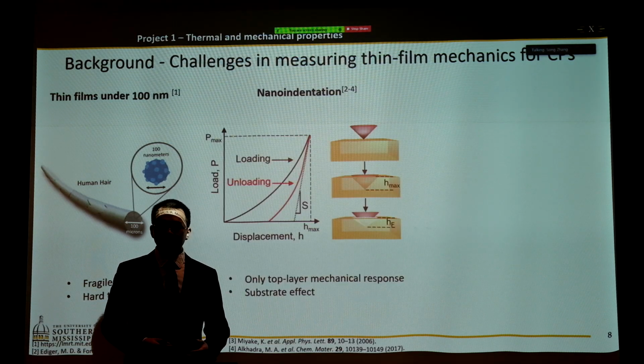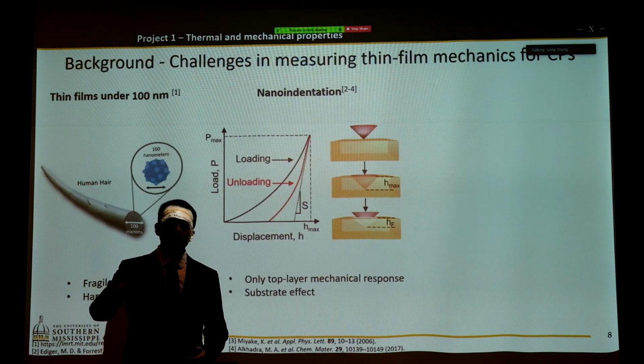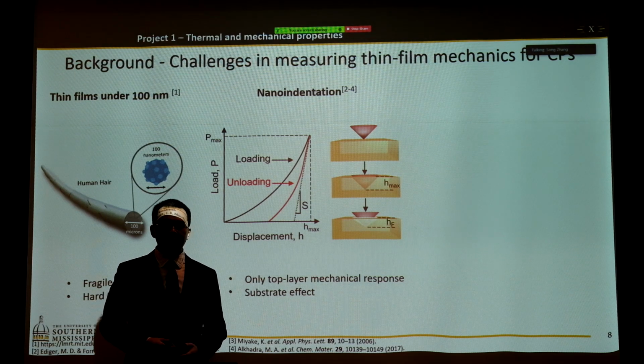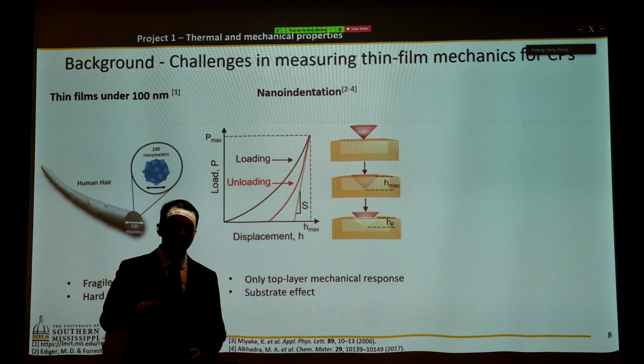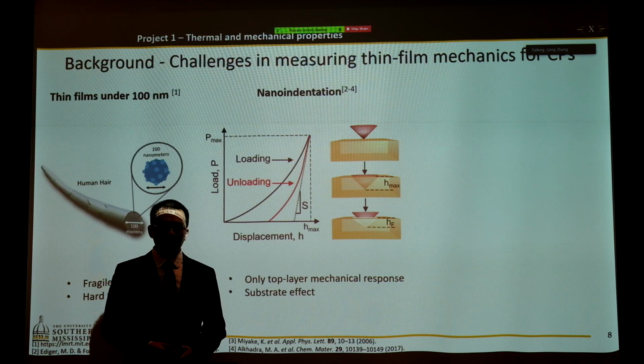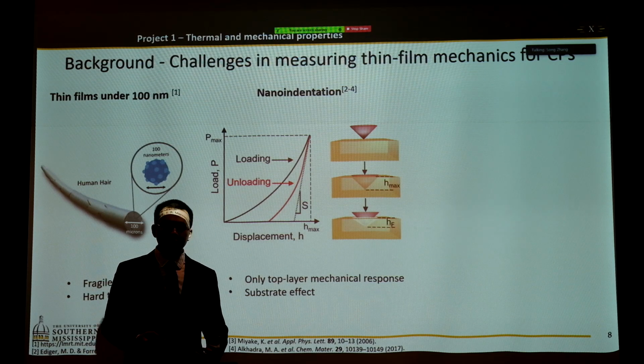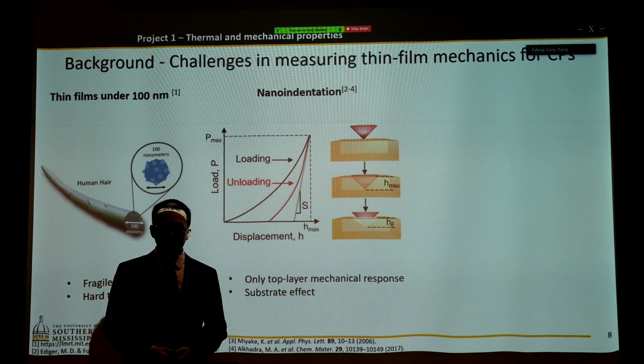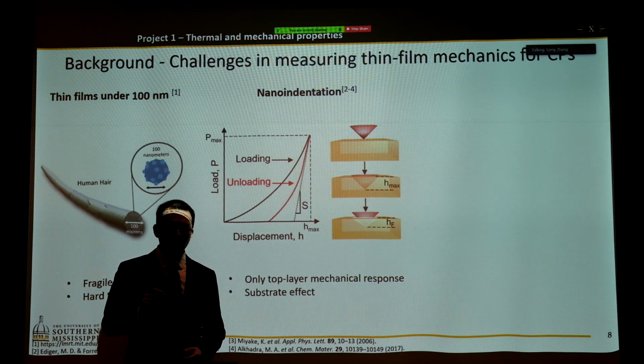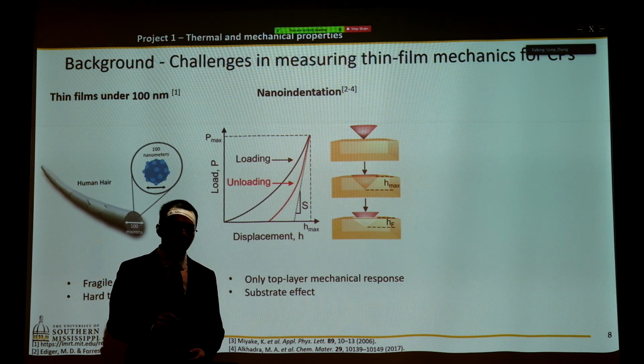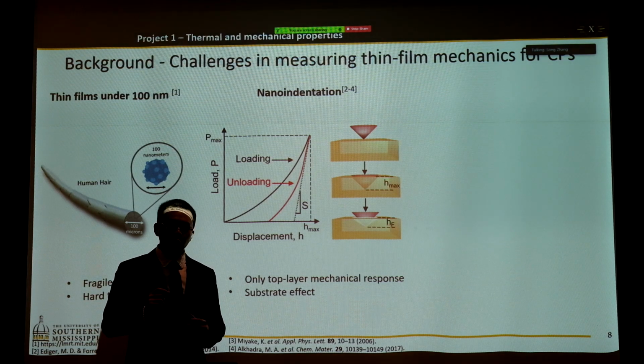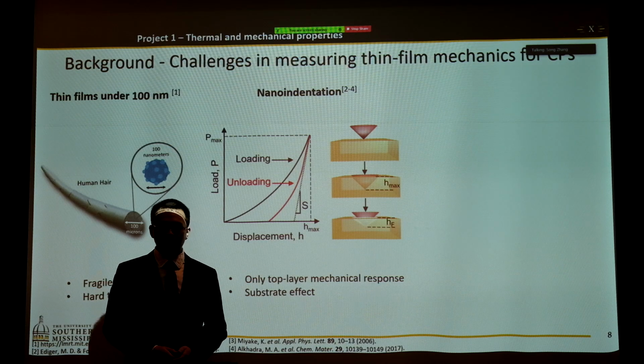For example, nano indentation. You apply an out-of-plane load, like using an indenter, penetrate into the thin film and pull it out. Now you have a loading and unloading curve. Through that curve, you can extract the stiffness, the hardness, maybe fracture behavior. However, for ultra-thin polymeric thin films, it is super hard to use nano indentation to quantitatively determine the mechanical performance.